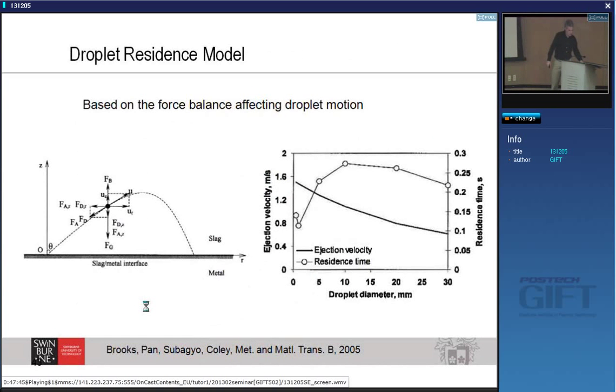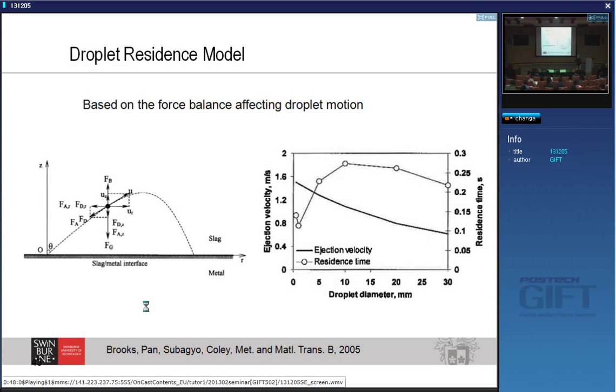Somebody asked me, they said, "Jeff, you're good at mathematics. Can you predict how long a droplet should spend in the slag?" So I did a force balance, right? I think you all know this. So we did a force balance on a droplet. And we found that the residence time of droplets based on this force balance would be about 0.1 to 0.2